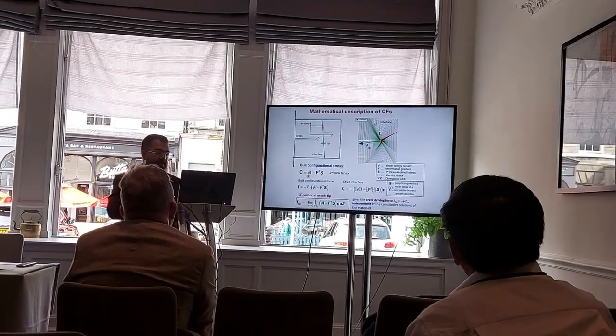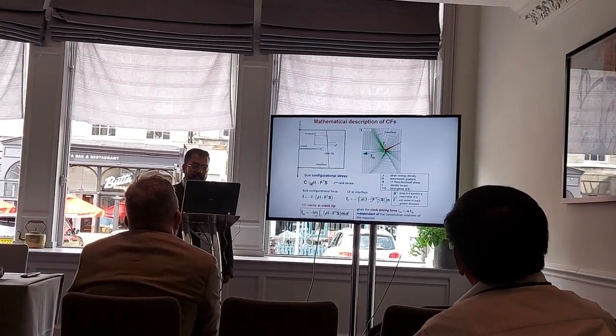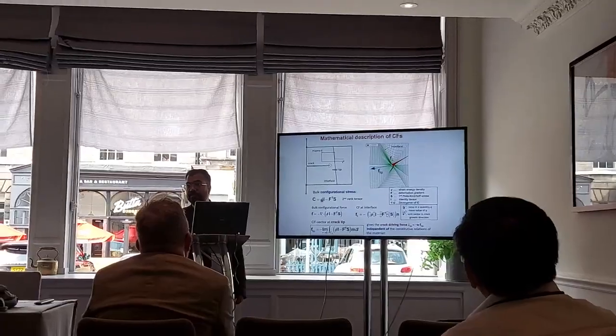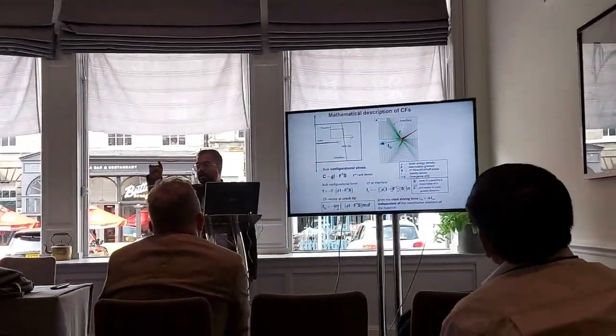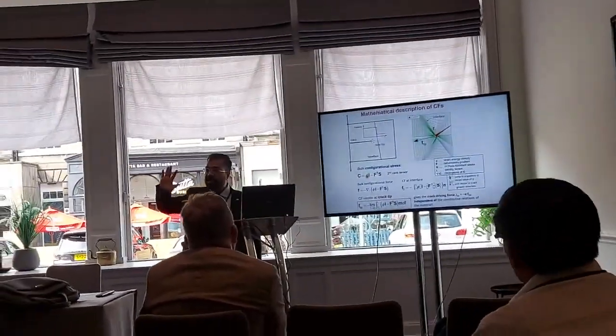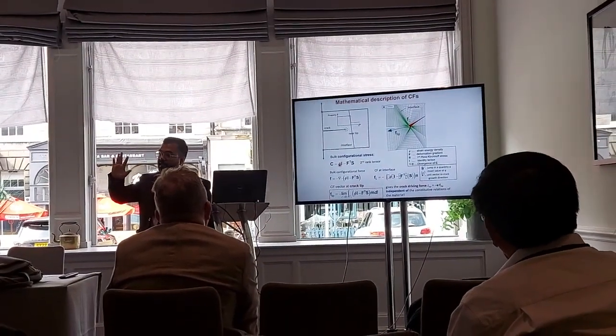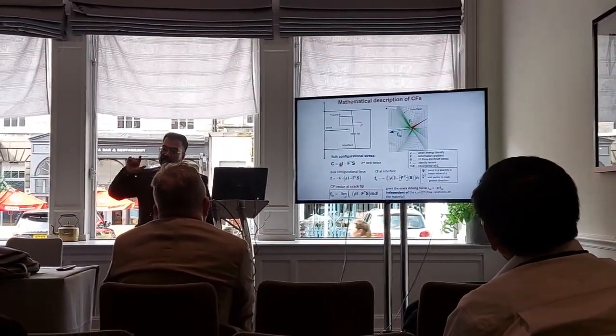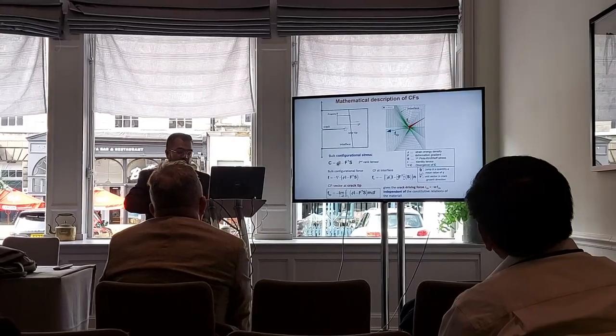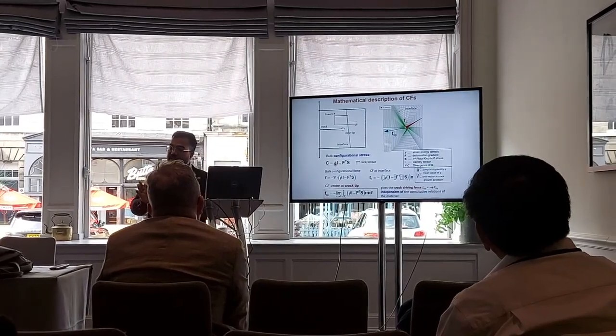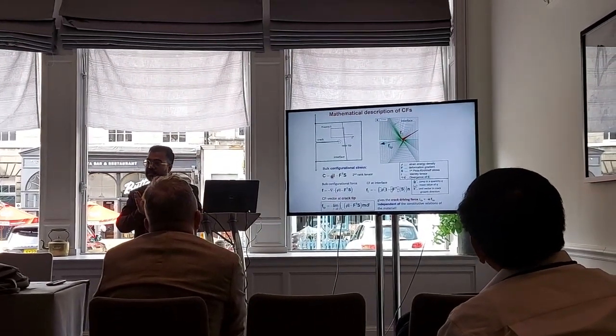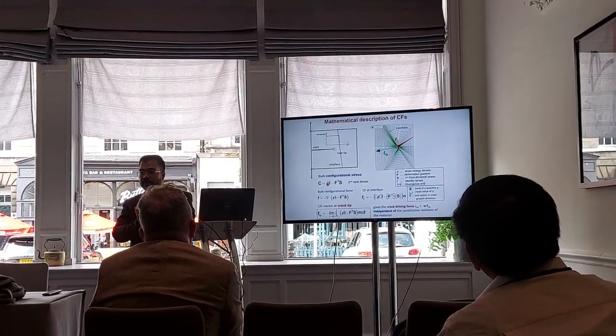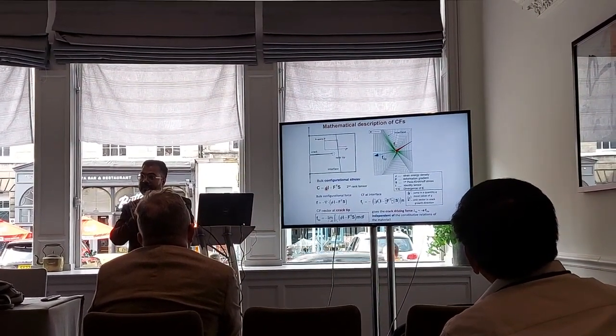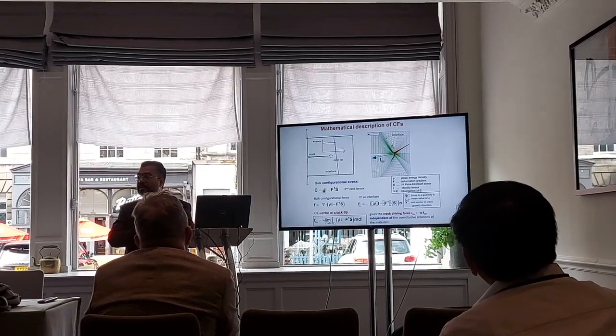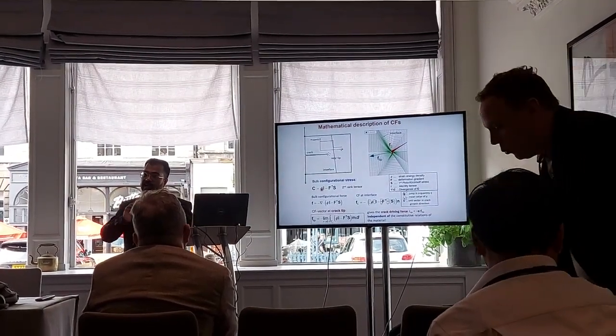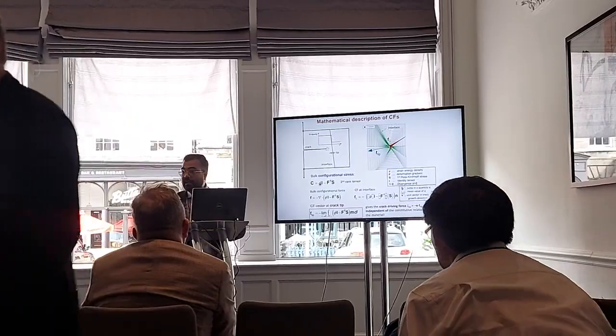If we assume the material to be non-linear elastic, the strain energy density term includes the whole area under the stress strain curve. That means it is assuming that the material is non-linear elastic. So if we include that in phi, then whatever we do is non-linear elastic, and when we take the projection of the J integral vector in the direction of expected crack growth, we get exactly the same J integral as given by Rice. So that is equal to the conventional J integral. But that is not the truth.